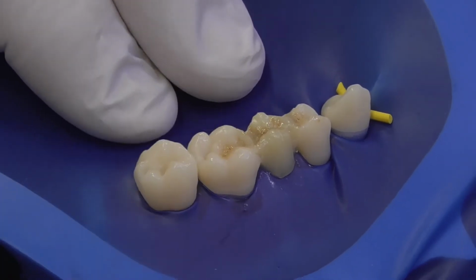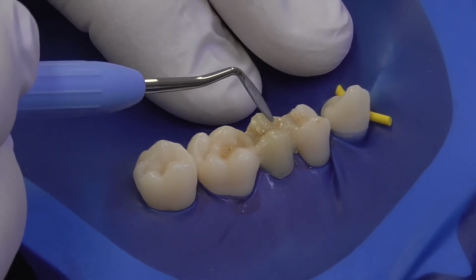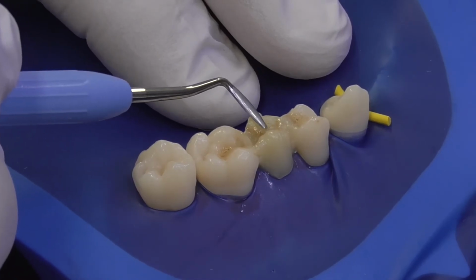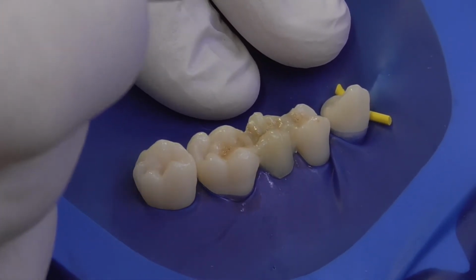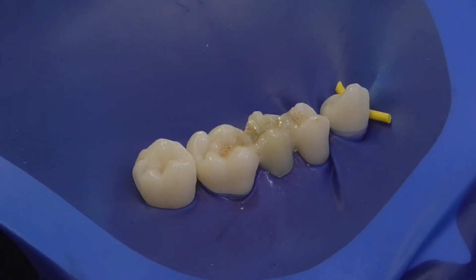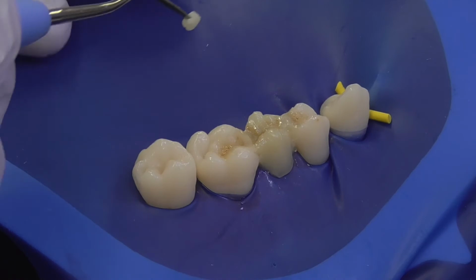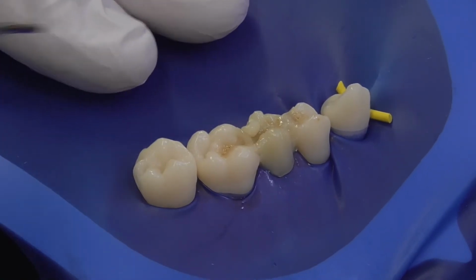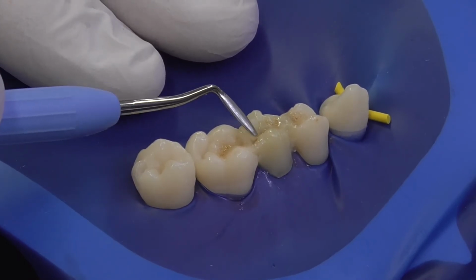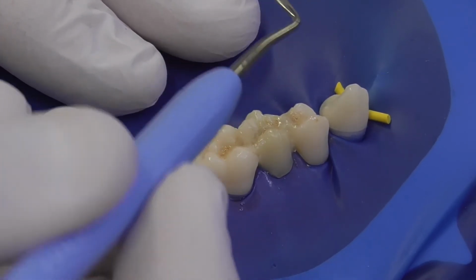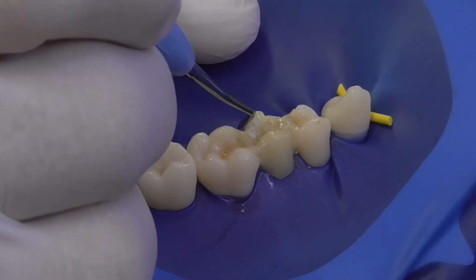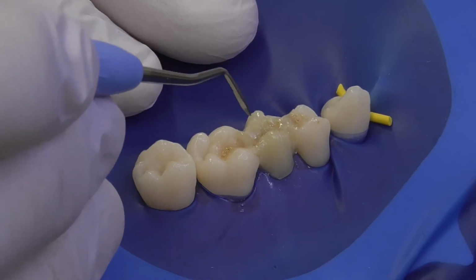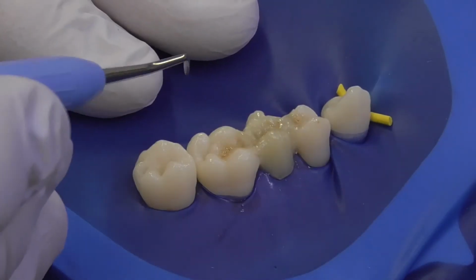After applying the characterization paint, we start the final light curing of the restoration, and also check that there are no gaps anywhere in the construction, especially between the natural tooth surface and composite resin, because minor gaps are potential signs of secondary caries. So we will now seal all gaps that can be seen in this connector region, which combines the abutment and a pontic as one bridgework.